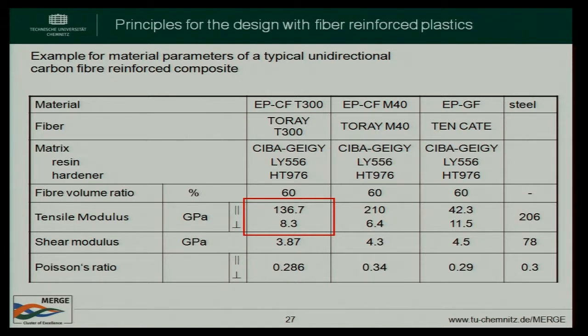And as an example, you see it here. This is a typical carbon fiber reinforced composite material, with all fibers in one direction, a so-called unidirectional layer. And you have here all the material parameters you need. So you see how many there are compared to steel. For steel you have one tensile modulus, one shear modulus, more or less one strength, and one Poisson ratio. Here, let's say this is a typical composite made from an epoxy thermoset matrix, a carbon fiber with a fiber volume ratio of 60%.